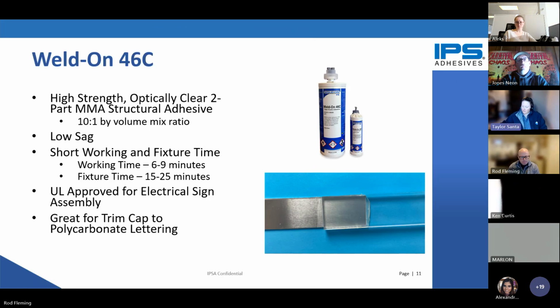All right, so next up in the line is the Weld-On 46C. So this is, again, a 10-to-1 MMA structural adhesive, high strength. The reason this product was designed was to have an optically clear bond whenever you're bonding clear acrylic to aluminum or any metals, and you want to be able to shine light through without having a visible seam. This product was designed for that.